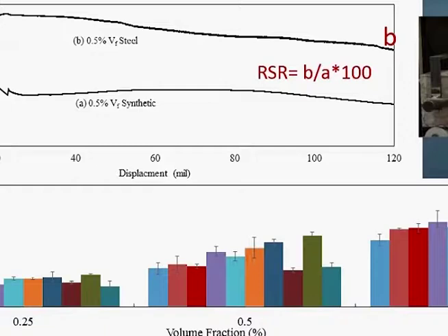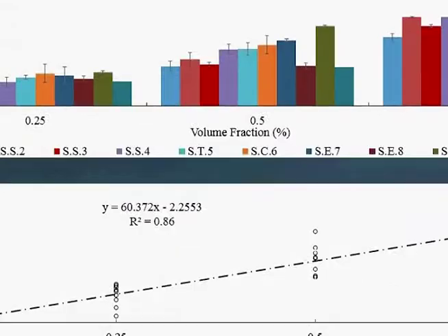If we run this kind of test, which is called the ASTM C1609 test, we apply a displacement-controlled load and get a peak load. Because of the fiber, the load does not go down to zero; rather, it sustains some load. We measure the load at 120 mils displacement, and divided by the peak load, we get the residual strength ratio. So that increases with the fiber, not the modulus of rupture.